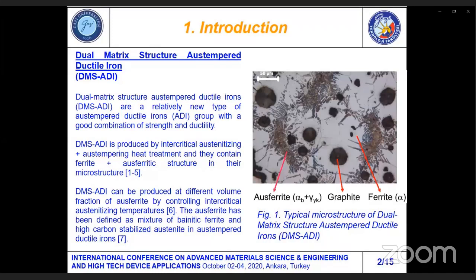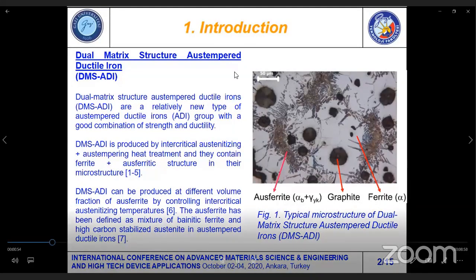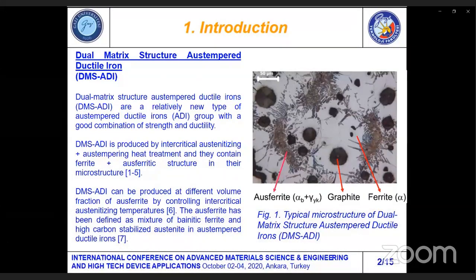Dual-matrix structure austempered ductile irons are a relatively new type of austempered ductile iron group with a good combination of strength and ductility. Dual-matrix structure austempered ductile iron is produced by intercritical austenitizing plus austempering heat treatment, and contains ferrite plus ausferrite structure in its microstructure. It can be produced at different volume fractions of ausferrite by controlling the intercritical austenitizing temperature. The ausferrite has been defined as a mixture of bainitic ferrite and high carbon stabilized austenite in the austempered ductile irons. You are seeing typical dual-matrix structure austempered ductile iron micrographs in Figure 1. The brown color is ausferrite, the white color is ferrite, and the black globules are graphite.